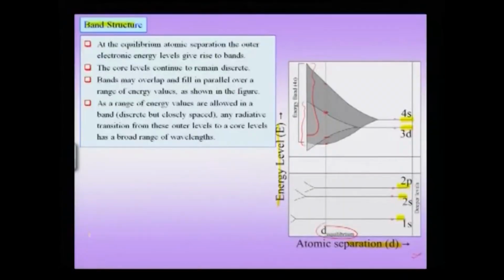There is some more detail about these 3D and 4s bands and their overlaps, which does not become obvious when you look at a diagram like an energy atomic separation diagram, and therefore, we will take up something known as the density of states diagram very soon. So, the message of the slide is that at equilibrium atomic separation, the outer electronic energy levels give rise to bands, while the core levels continue to remain discrete, that means they still have the atomic character. Bands may overlap and fill in parallel over a range of energy values as shown in the figure here.